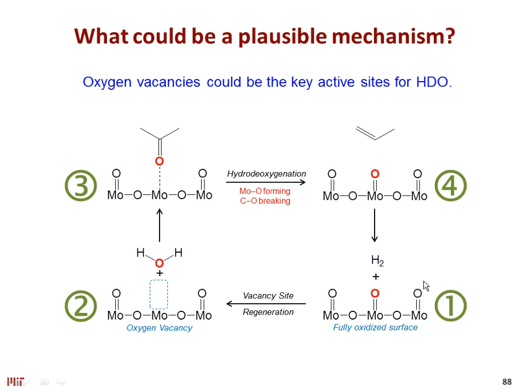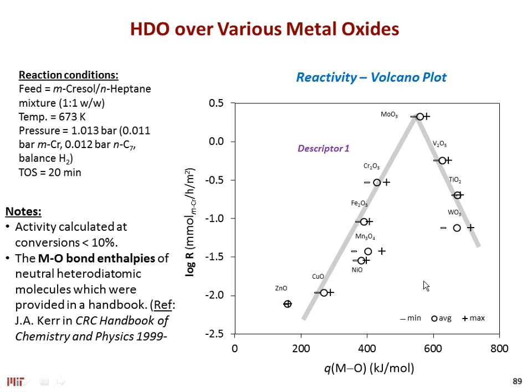So we started looking a little bit more at what could be happening. We started looking at what is going on at the surface. So this is a very simplistic depiction of what we think is happening. We started looking at the rates and the bond enthalpies. We knew that these oxygen vacancies are important. In this case, we're plotting the bond enthalpy as a function of our observed rate, and we see one of these classic volcano relationships with molybdenum oxide at the top. So we knew somehow these vacancies are important in the catalytic cycle.